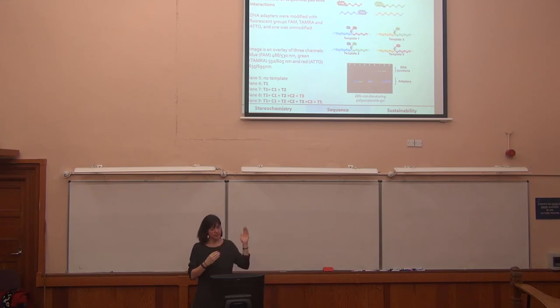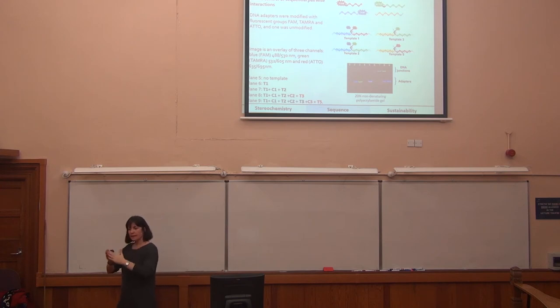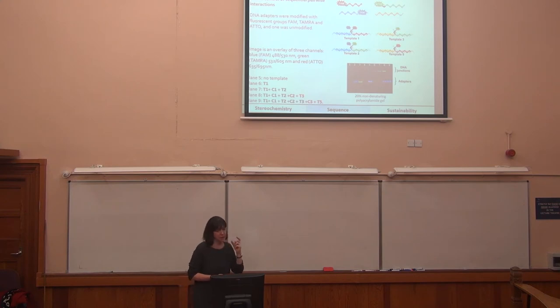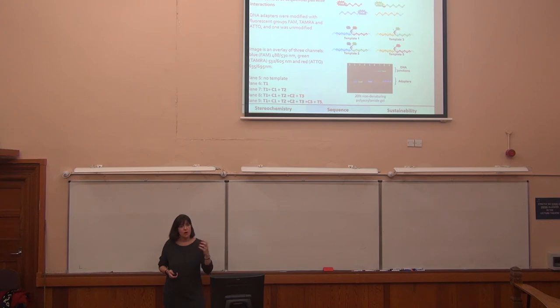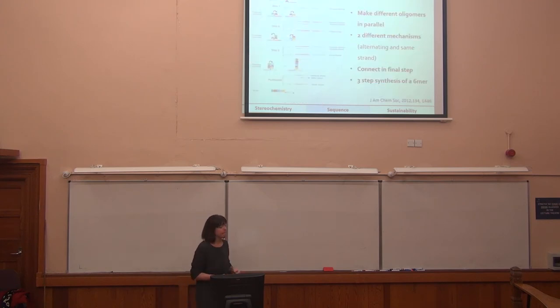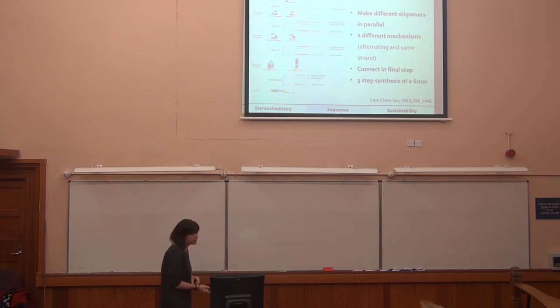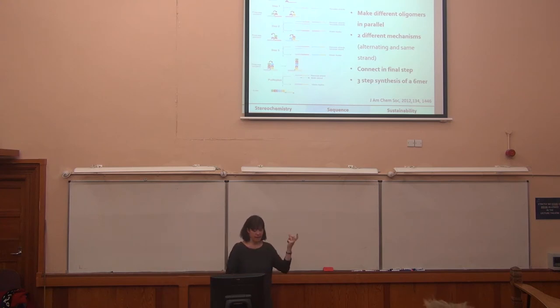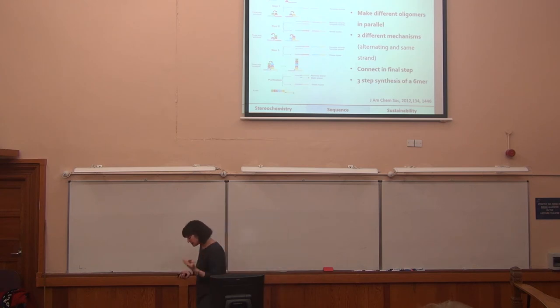So we took this right through, and we were able to make and form these junctions, and then wipe the instructions. Being able to do that in one pot meant that we can start to use instructions to control the sequence of reactions rather than using the addition of the reactive groups. And this allowed us to do even more by playing about with the mechanism and looking at either an alternating or a same strand mechanism.